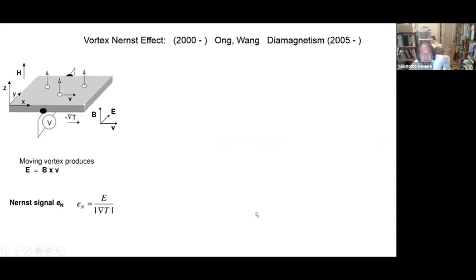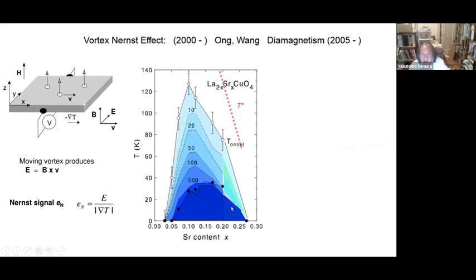And so first of them is the vortex Nernst effect onset temperature. So in 2000 and about 10 years from that time, Ong has pioneered measuring the vortex Nernst effect. And for example, this is LSCO, and this is the onset temperature of the vortex Nernst effect. The real TC is here, okay? It's much lower temperature. And for example, in the underdoped region, there's about a factor of 4 or 5 difference between the onset temperature of Nernst effect and real TC.